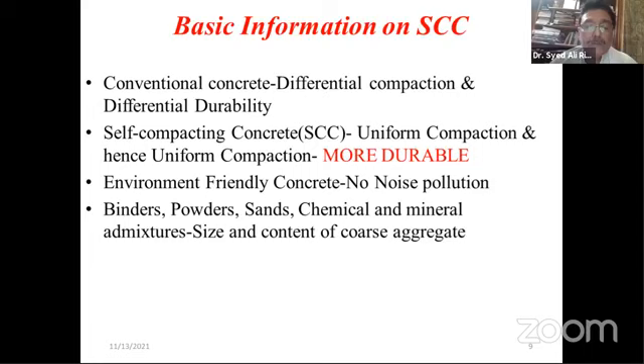The only thing that we should look for is that in case of coarse aggregates, the size and the content of coarse aggregate is slightly dropped. Because when this SCC flows, there is an internal friction between different phases. And if there is more internal friction, it will take more time to flow, and hence it will not be an SCC. Therefore, we choose a slightly low coarse aggregate content, and its size in actual practice can be limited to around 16 millimeters or so.